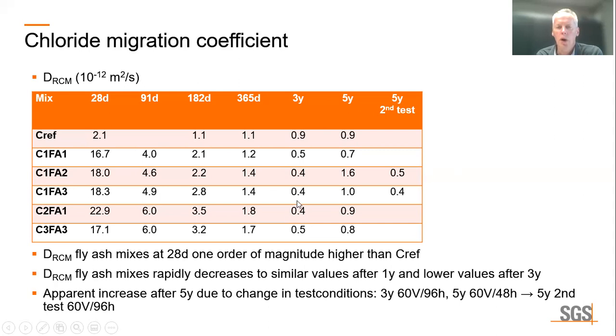After 3 years, we are at the outer limit of the NT Build standard, where we have to apply the maximum voltage and maximum test duration, whereas after 5 years, the test duration was 1 step lower.